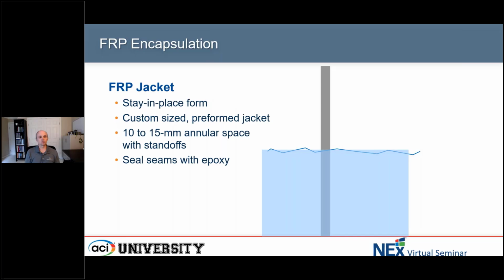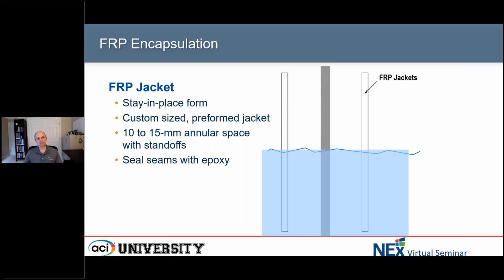Okay, so assuming that we can now get through the surface prep piece of this and then move on to installing a repair system, when we're talking about these FRP systems, they're really designed to more or less encapsulate the underwater structure. So again, there's a lot of different varieties of this, but generally what these entail is using the FRP material as essentially a stay-in-place form that goes around the concrete structure, and then that stay-in-place form is filled with a grout to encapsulate that underwater member, whatever it may be.